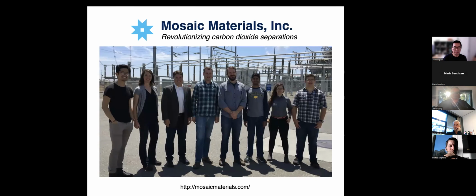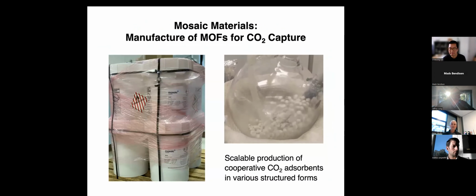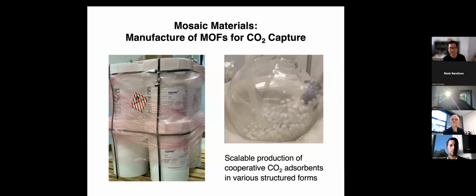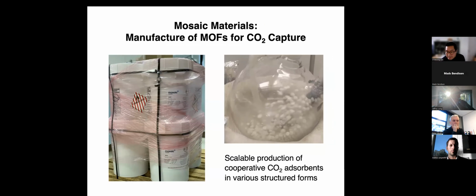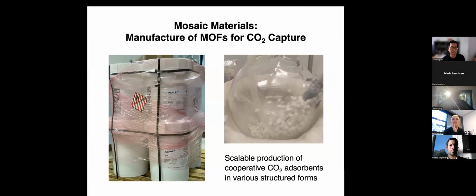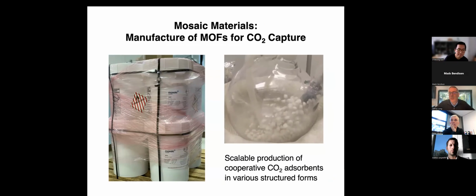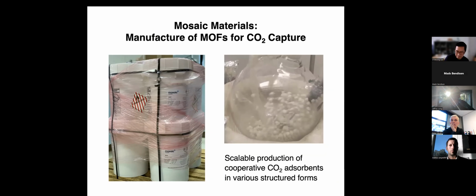So those materials were interesting, and actually the PhD student who initially discovered the cooperative CO2 adsorbents was Tom McDonald, and together we started a company to try and scale up and test these materials in a practical separation. So this company is Mosaic Materials. Actually, Ju Wung, as a postdoc, started out working part-time in starting this company. But the real technology that was developed there was, how do you make these materials inexpensively at large scale? And how do you make them in structured forms that are robust and don't pulverize under working conditions? And so at the right, you can see MOF pellets being bashed around, testing and showing that they're not coming apart.